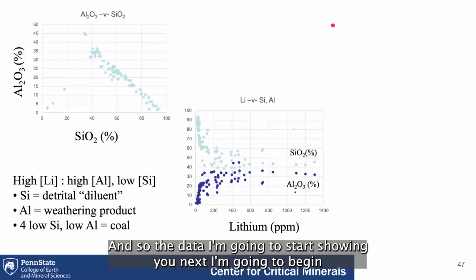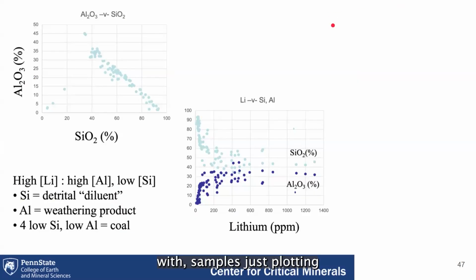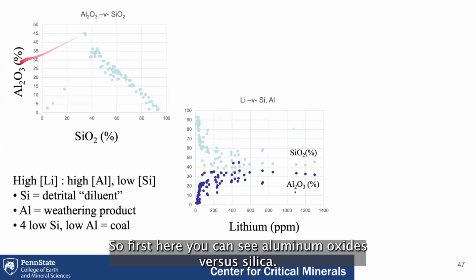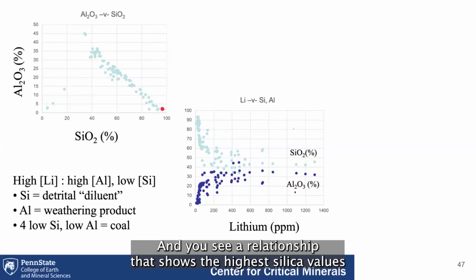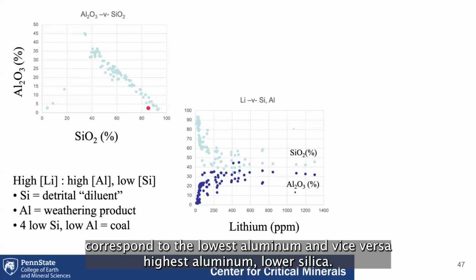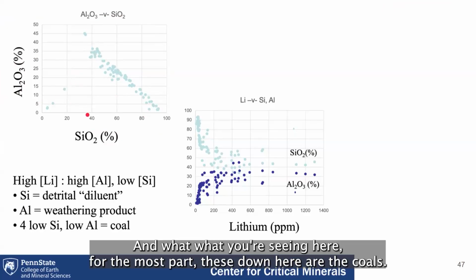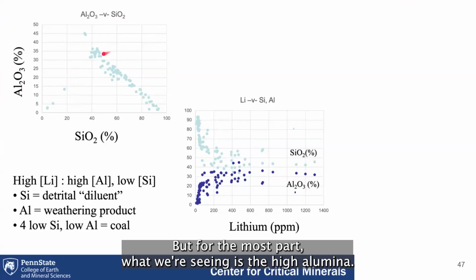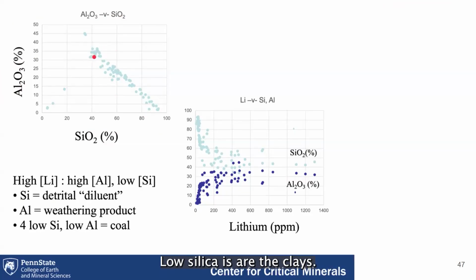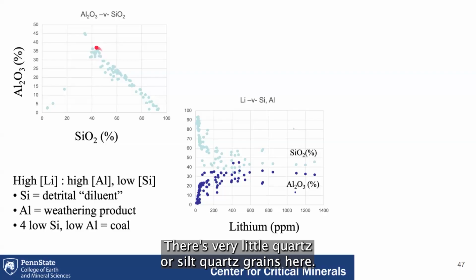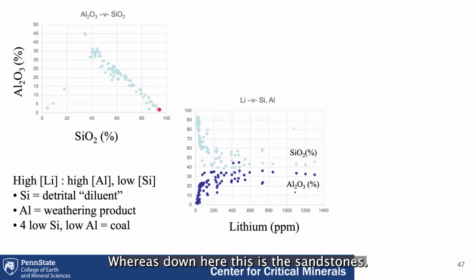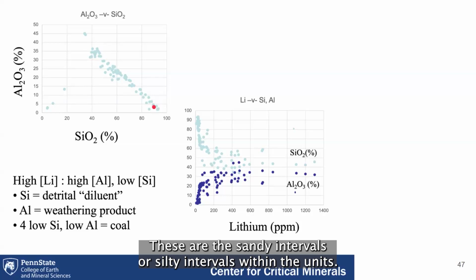And so the data I'm going to start showing you next, I'm going to begin with samples, just plotting all the information in a couple plots. So first here you can see aluminum oxide versus silica. And you see a relationship that shows the highest silica values correspond to the lowest alumina, and vice versa, highest alumina, lower silica. And what you're seeing here, for the most part, these down here are the coals. But for the most part, what we're seeing is the high alumina, low silica are the clays. There's very little quartz or silt quartz grains here. Whereas down here, this is the sandstones. These are the sandy intervals or silty intervals within the units.